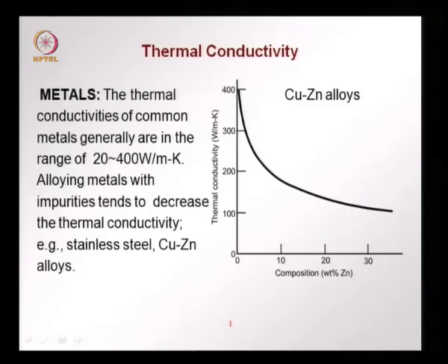What are the ranges of thermal conductivities? In metals we have a range of 20 to 400 watt per meter Kelvin. We also see that as the composition of the material changes, the thermal conductivity changes. On the right hand side we have this graph showing a copper zinc alloy, composition varying as shown in the x axis, and the thermal conductivity varying with the composition like this.